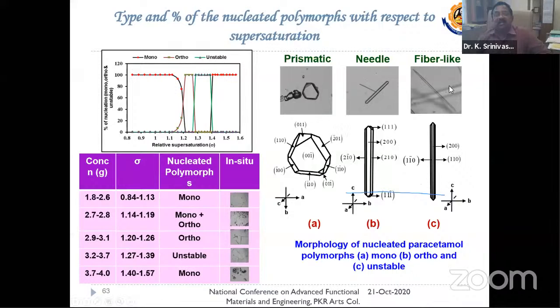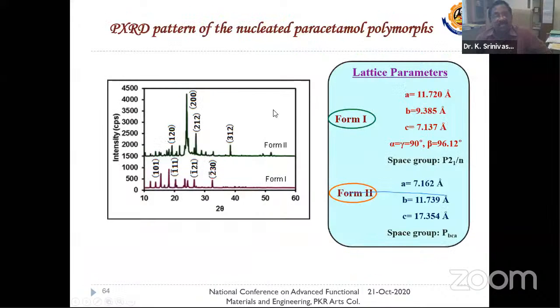And three polymorphs: prismatic, needles, and fiber-like. The morphology investigation is very, very important to study their application-oriented properties. And then the confirmation is by X-ray diffraction. This is a powder X-ray diffraction of form 1 and form 2. There's a distinction here, and the refined lattice parameters. Okay. So this is an ultimate confirmation of the polymorphs after their growth.